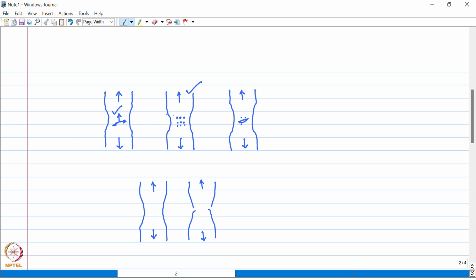So as the material is strained further, as the straining is continued, these voids will grow and coalesce together, leading to the formation of a crack at the center. So the void nucleation and coalescence leads to formation of a central crack, as you could see over here.